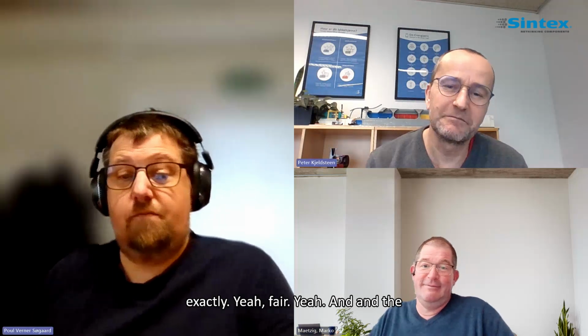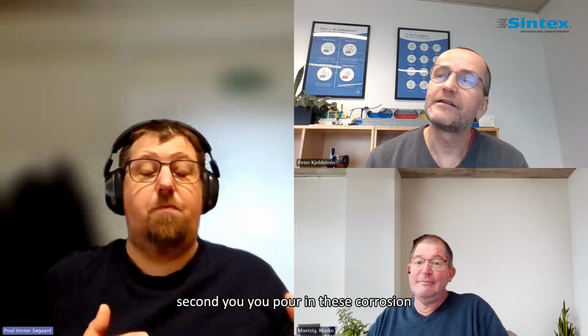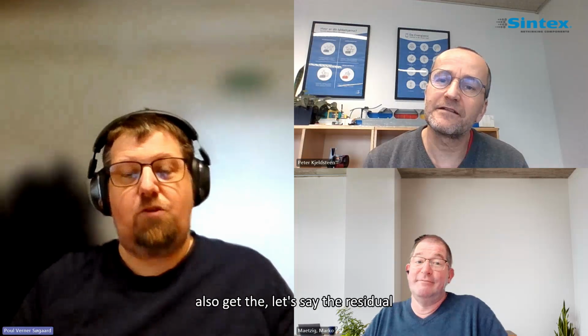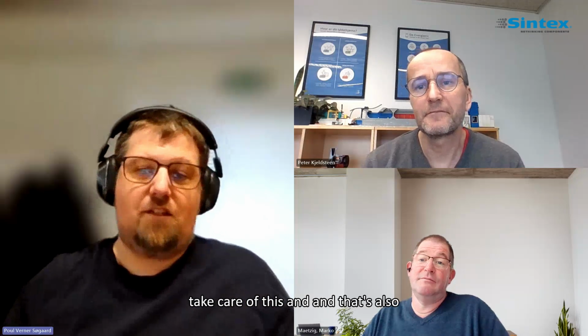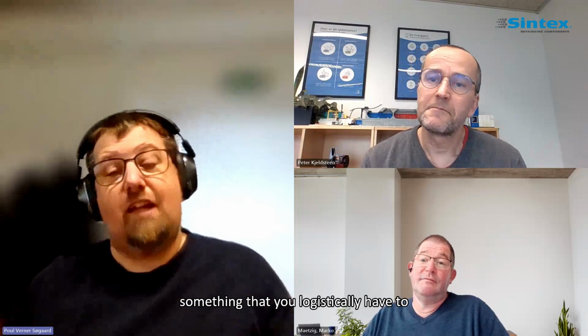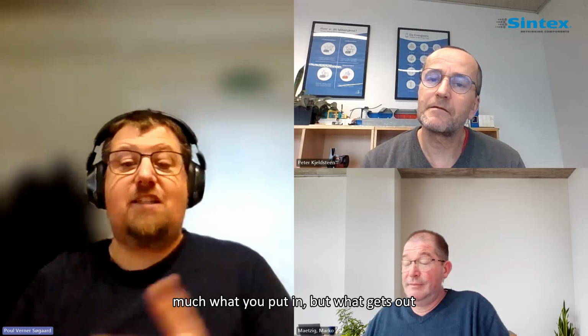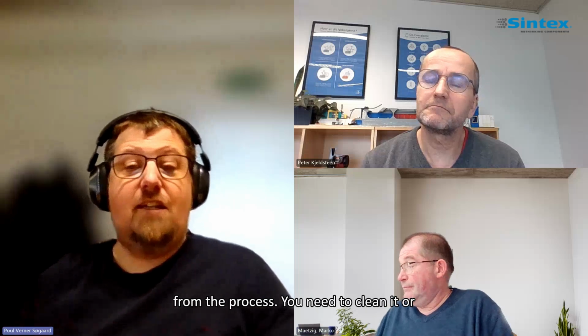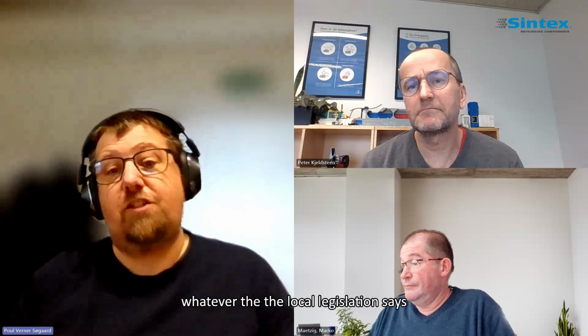Yeah, exactly, fair. And in a second, when you pour these corrosion inhibitors into the water system, you also get the residual water from the debinding. You need to take care of this, and that's also something that you logistically have to take care of. Not so much what you put in, but what gets out from the process. You need to clean it, or do whatever the local legislation says you have to do. So there are disadvantages in this also.